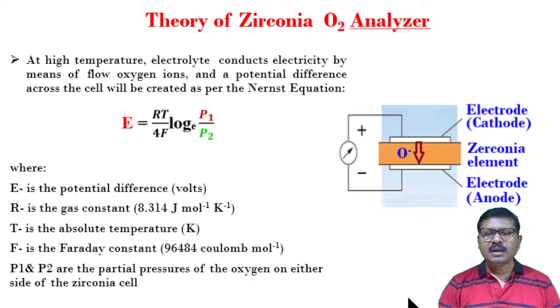At high temperature, the electrolyte conducts electricity by means of the flow of oxygen ions, and a potential difference across the cell is created as per the Nernst equation. E is equal to RT by 4F log e P1 by P2, where E is the developed potential across the zirconia element, R is the gas constant 8.314 joule per mole per Kelvin, T is the absolute temperature in Kelvin, F is the Faraday constant 96484 coulombs per mole, and P1 and P2 are the partial pressures of the oxygen on either side of the zirconia cell.